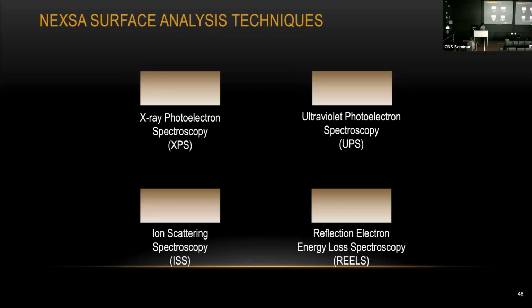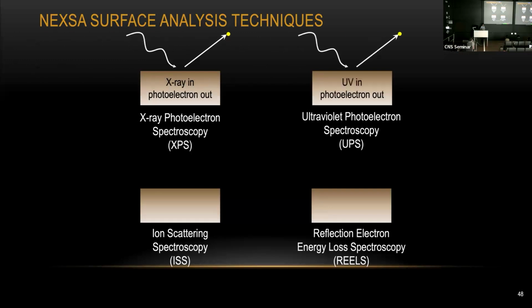So here is a cartoon to illustrate what all these four techniques can do. For XPS, again, you're hitting your sample with an X-ray beam and getting photoelectrons out. For UPS, you're hitting your sample with UV light and still getting photoelectrons out. That's why these two measurements are called photoemission. For ion scattering, you hit your sample with much heavier ions. The heavy ion hits the surface, loses some energy based on the surface atom, and goes back to the detector. It's the same incident particle hitting the surface and going back to the detector, and we simply measure the energy before and after. Then we can understand what kind of elements you have on your surface.